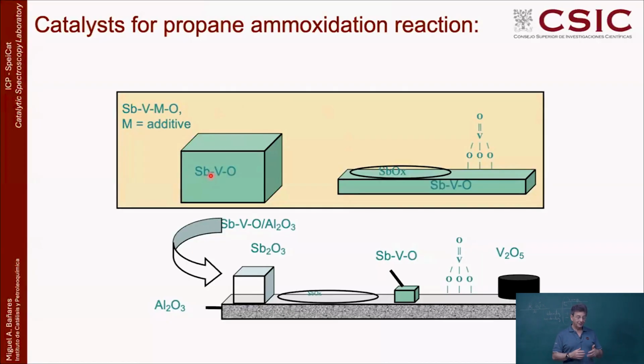How do we do that? Similar to the nanoceria particles of the other day, we put a very small amount of this vanadium and antimony on a support. A very small amount means around one monolayer, maybe 2 monolayers, maybe 3 monolayers, maybe below monolayer, and make some kind of aggregate. Well, it turns out that vanadium and antimony are mainly non-interacting, which means that at a low coverage below monolayer, they basically stay one next to the other, and antimony is hardly reactive.